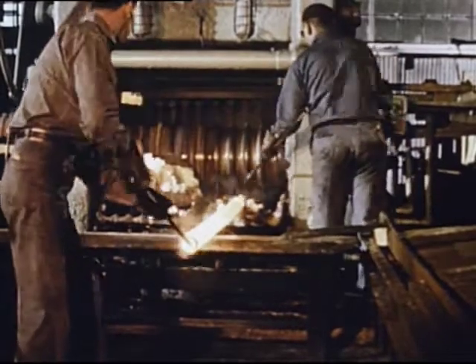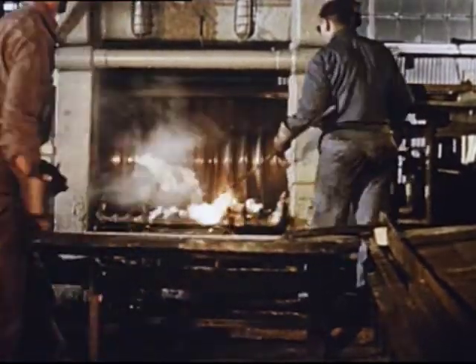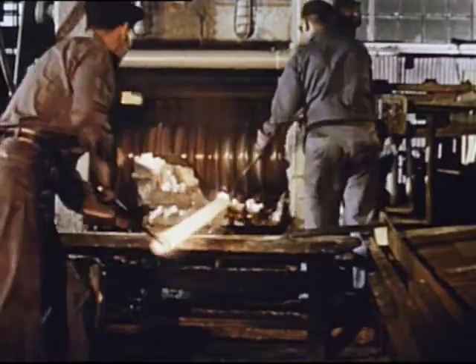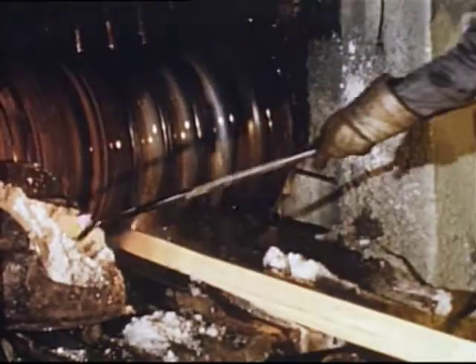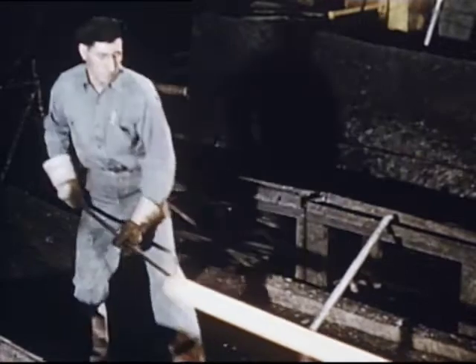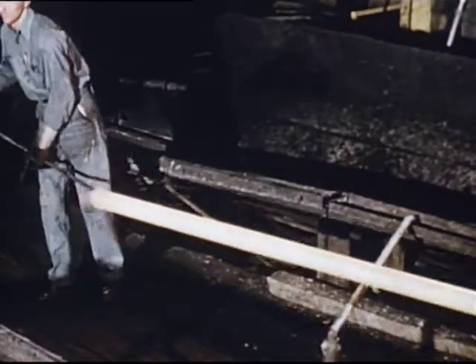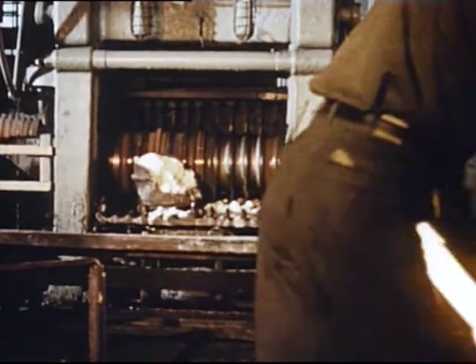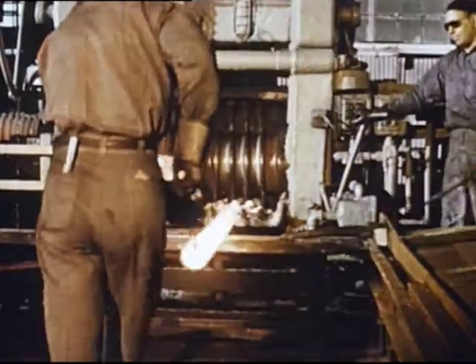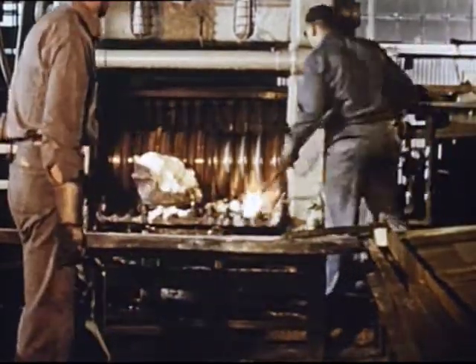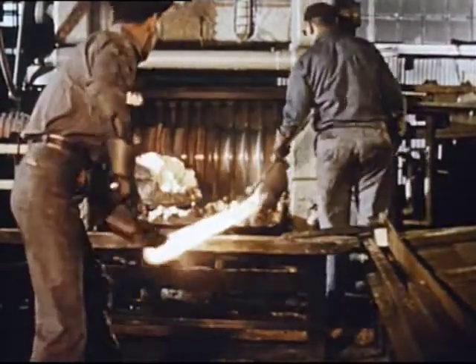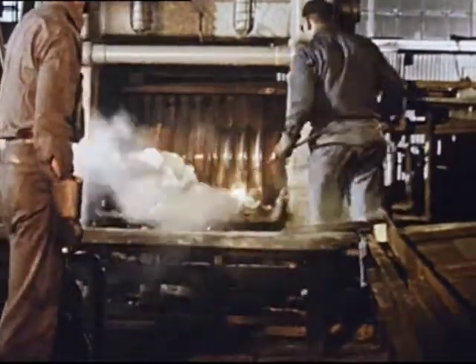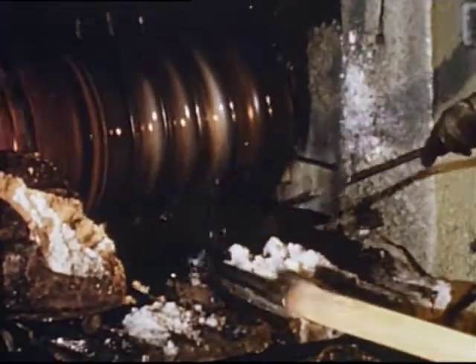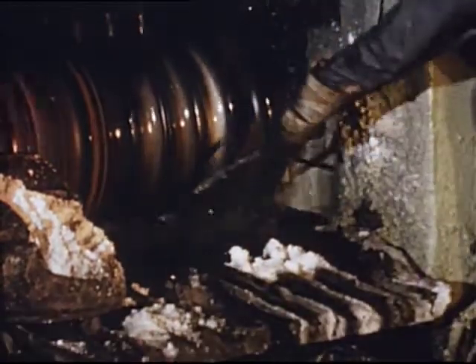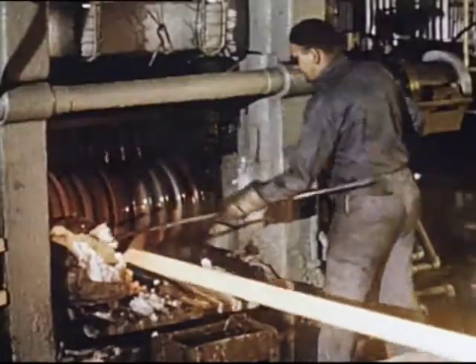Here, the highest skill is required of men in the job of catching the red-hot steel tube as it comes roaring from the mill, sending it back again and again. Each time, a forging action takes place as the tube passes between the water-cooled grooves of revolving rolls. Each pass reduces the diameter and wall thickness of the tube, refines both inside and outside surfaces, and increases the length.